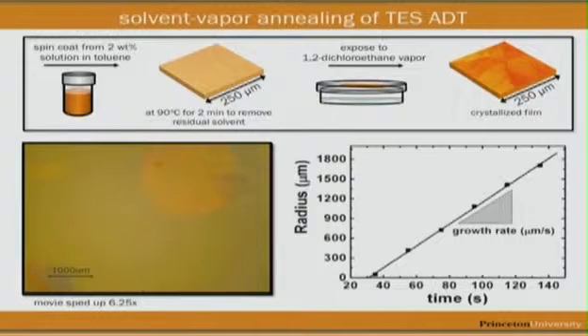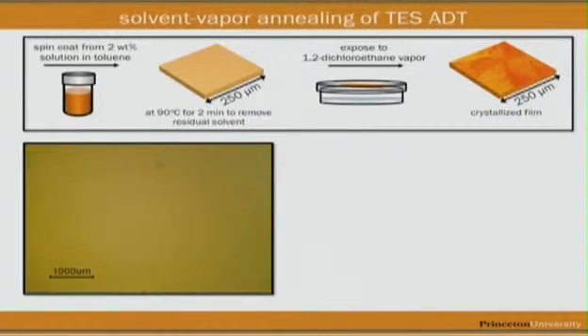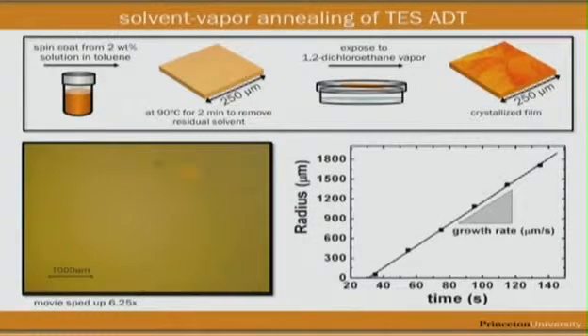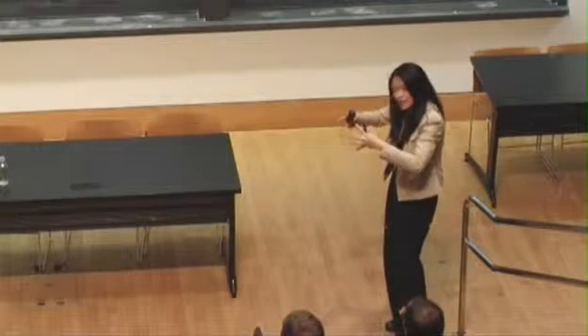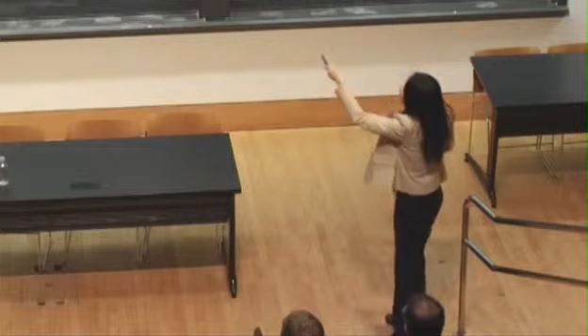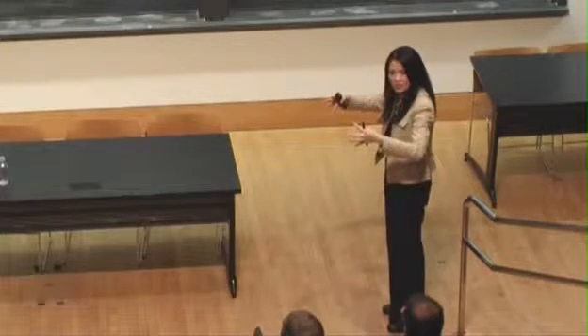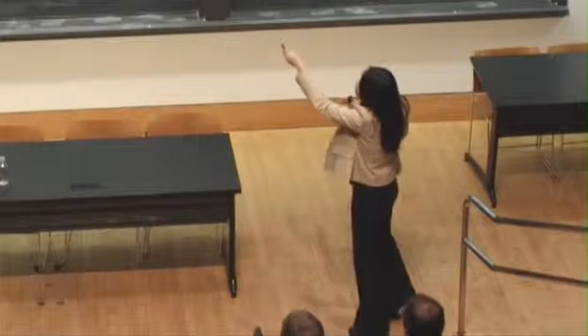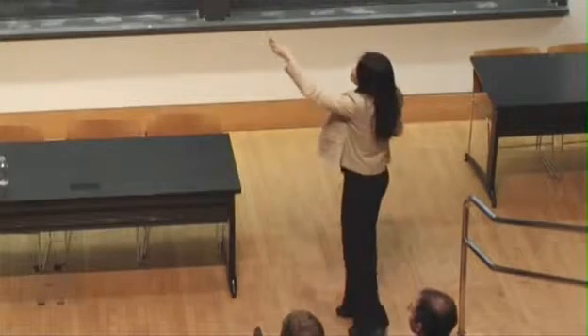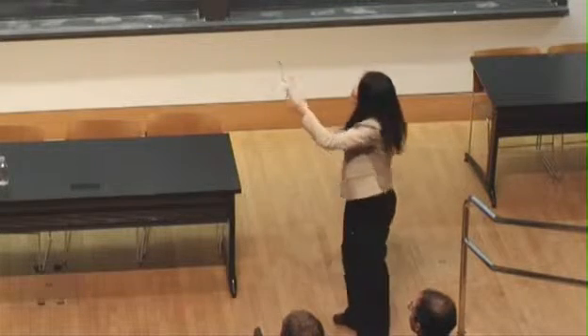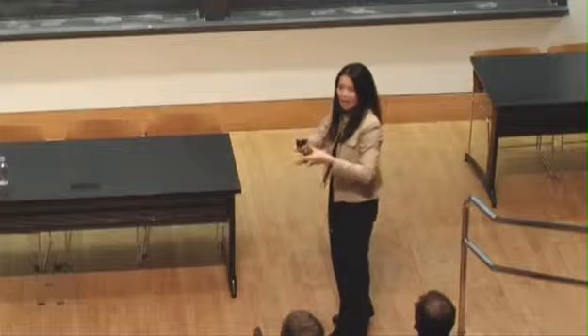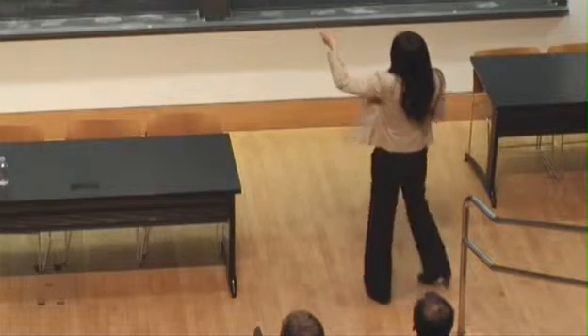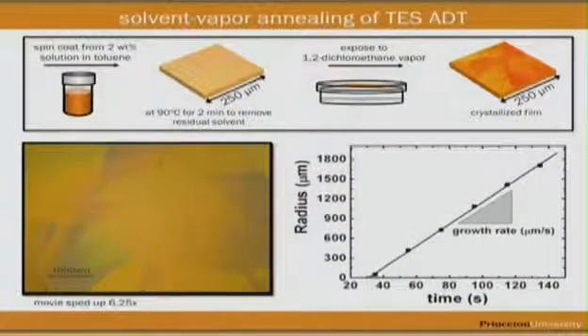So I don't know whether you can see it. The contrast is pretty bad. How this happens. So this is during the solvent vapor annealing process. So I'll run it again. So when we expose the solvent vapor to this film, it crystallizes. It starts out as a nucleation point, and then when crystallization happens, it basically radially spreads out. Okay? And so now this is all crystalline, and as it grows until this spherulite basically impinges on the neighboring spherulite, and so you form a boundary. Okay? These things are called spherulites because they start out round. Okay? We can track the radius as a function of time, and so we can extract a growth rate.